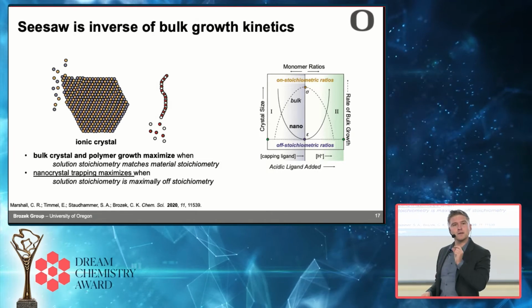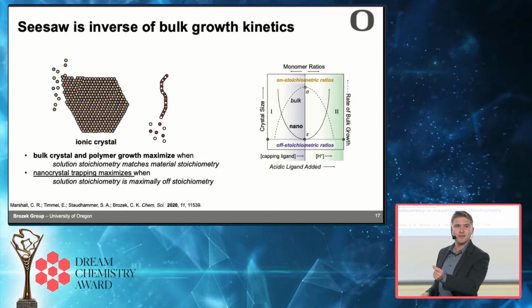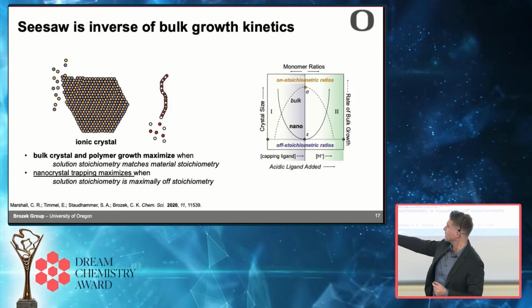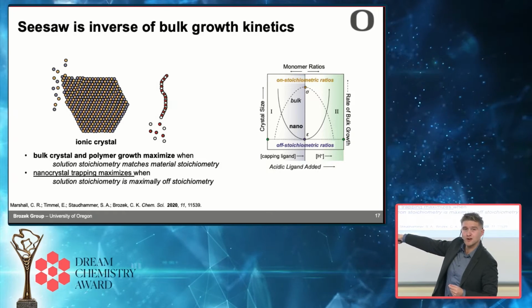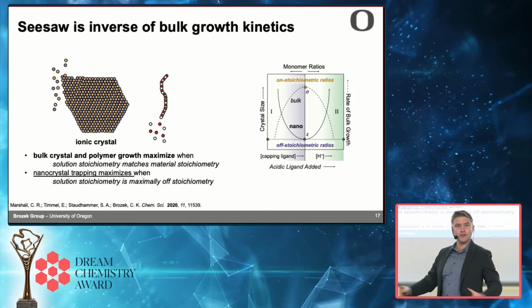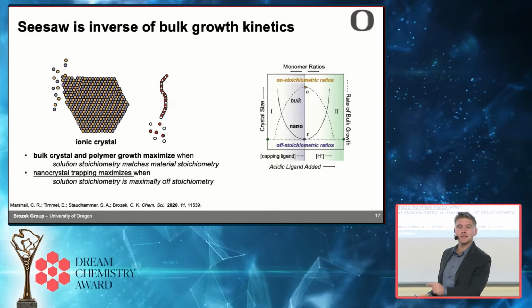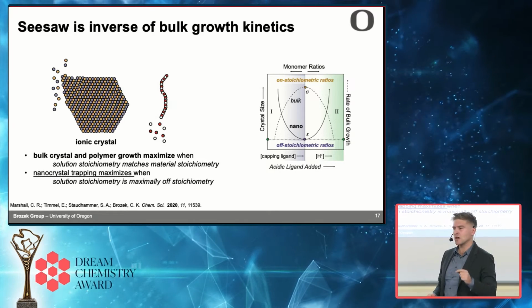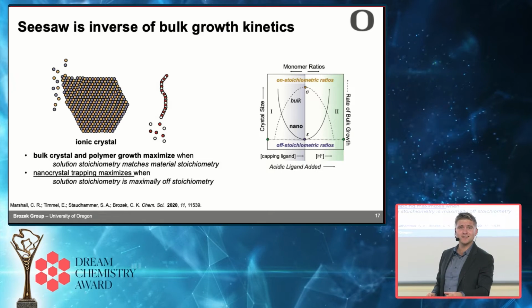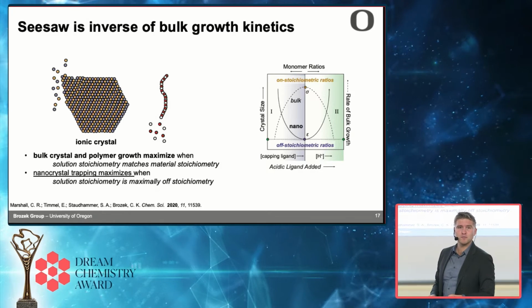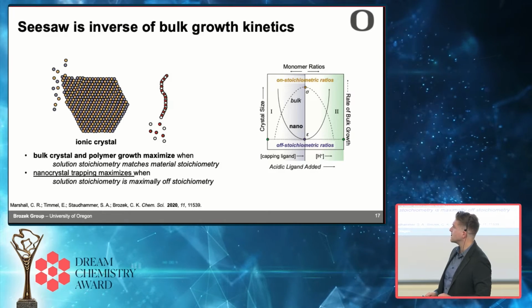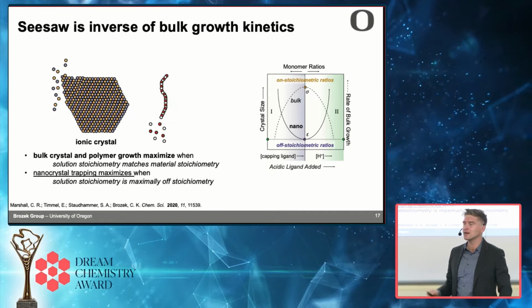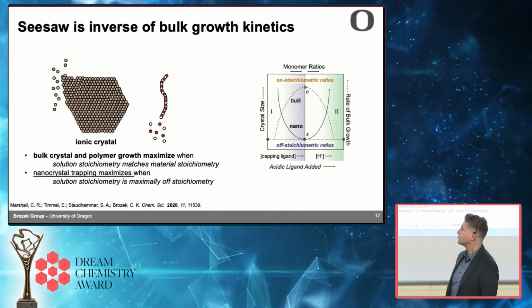Well, what we're saying is a perfect complement to that. You get the smallest nanocrystals when the stoichiometry of your reaction media looks as least as possible like the MOF you're trying to make. In other words, use a ton of excess linker and you're going to end up with really small MOF nanoparticles. So that was the idea. And so this is all complementary to how people think about these other ways that things grow.